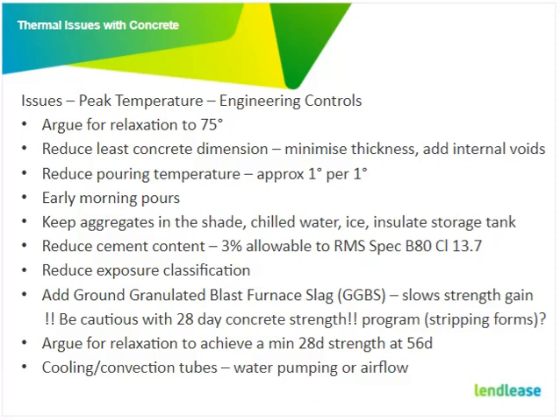Slag definitely helps, but slows your strength gain. So as I discussed before, be careful with your 28-day concrete strength. Slow strength gain means you've got to strip your forms a bit longer than what you normally would. So you're adding this to reduce your peak temperature, but then you get a program penalty. So you're addressing an issue that shouldn't need to be addressed, and you lose program. Another opportunity may be in the specification, maybe there's an argument to have the utilisation of minimum 28-day strength at the 56-day test.